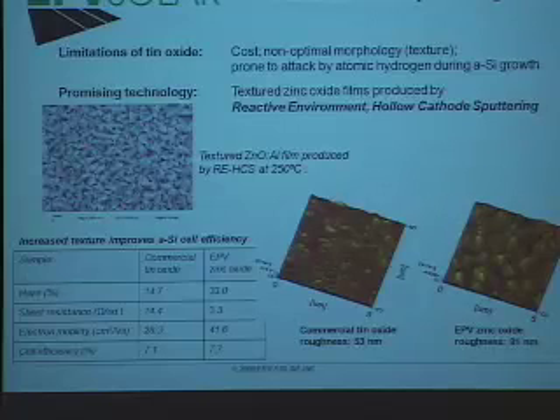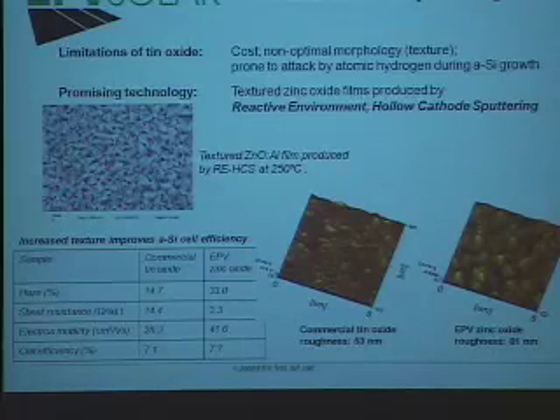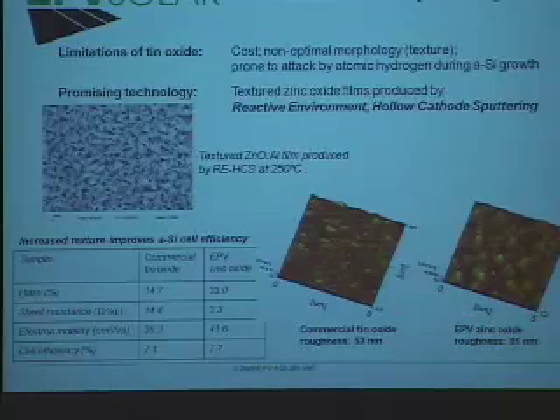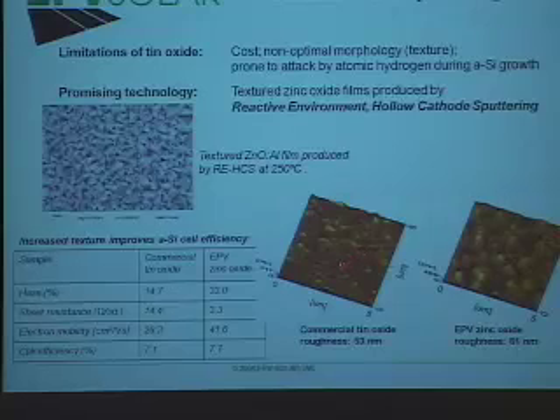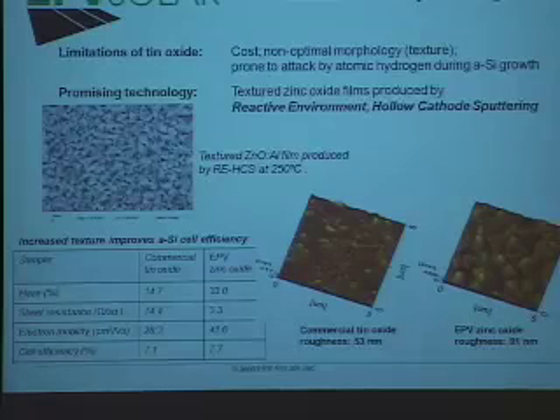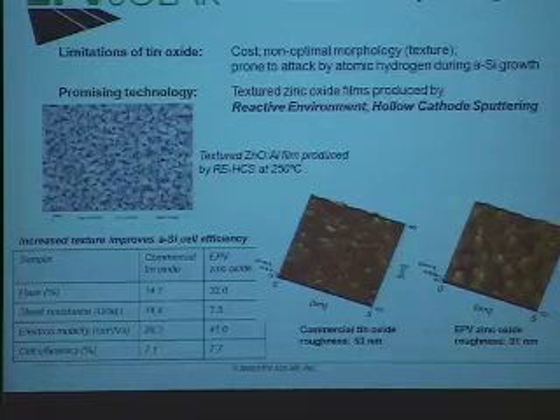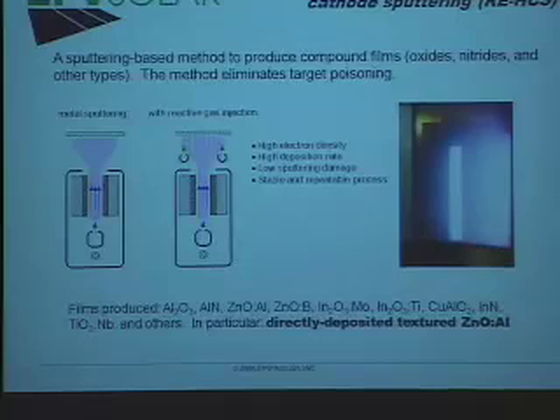This is a SEM micrograph of these films. They are not planar, they're very heavily textured. Our zinc oxide is more heavily textured than commercial tin oxide. Even with amorphous silicon, you get better results when you use our zinc oxide. So this is the principle of hollow cathode sputtering. Two facing targets, you sputter off the atoms and carry the atoms with the working gas to deposit on the substrate. For an oxide or a nitride, you introduce the reactive gas in the afterglow.